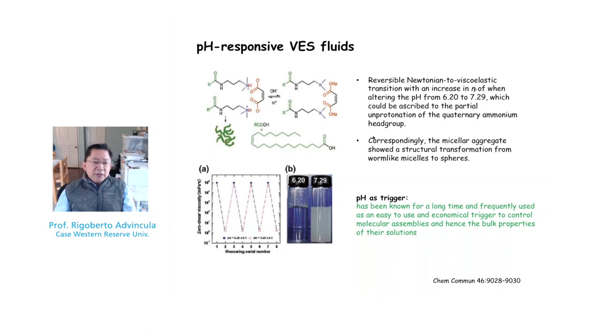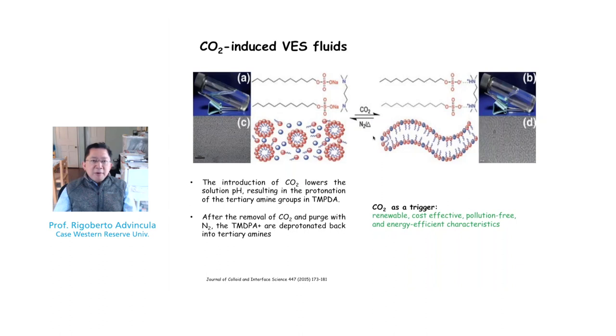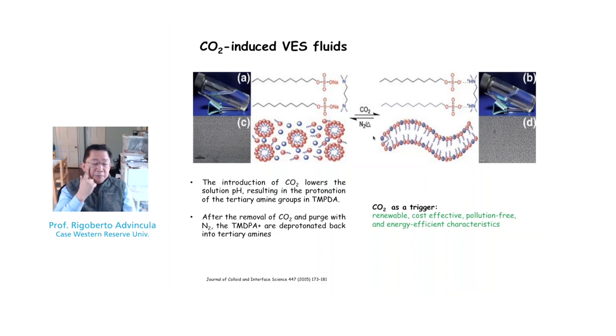Carbon dioxide gas (CO2) can also trigger a transition from spherical to worm-like micelles. This particular surfactant is sensitive to media acidity, resulting in improved stability of the worm-like micelle through complexation of a sulfonate group and a protonated diamine, resulting in higher viscosity. This is because CO2 lowers solution pH by forming carbonic acid. There are several other examples of VES that are pH, temperature, chemical, and enzymatically stimuli-responsive.